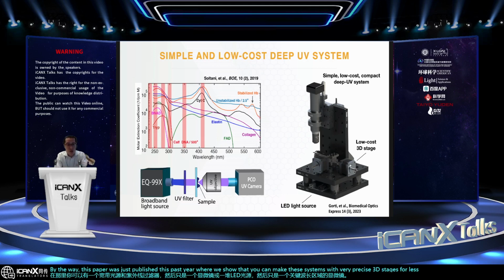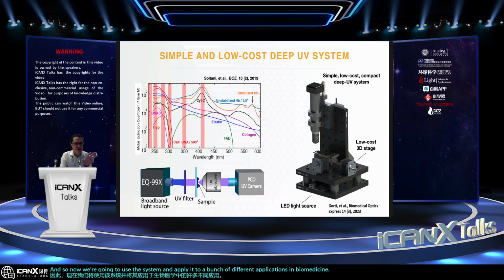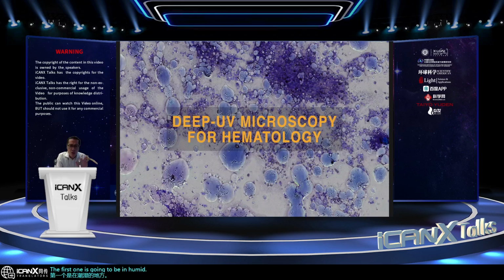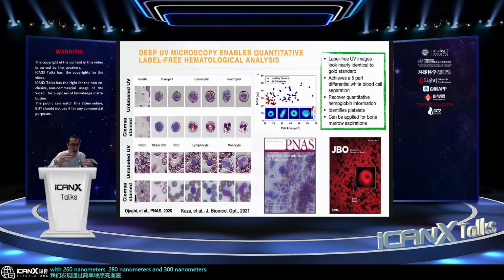And so now we're going to use the system and apply it to a bunch of different applications in biomedicine. The first one is going to be in hematology, where we found that by simply illuminating blood cells with 260 nanometers, 280 nanometers, and 300 nanometers, and weighting those three attenuation maps differently, we can recapitulate the gold standard stains for hematology, which are these Giemsa stains. And the agreement is just remarkable given the simplicity of UV microscopy.